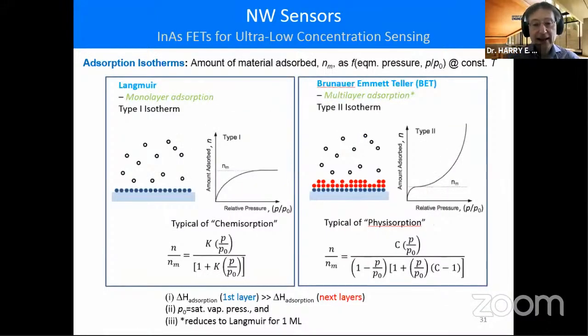I need to take a few minutes here just to deviate and make sure that you're aware of isotherms. So a very zero order look at that. If it were a single monolayer adsorption process, we would use the Langmuir isotherm, in which the amount of adsorbed material, Nm, is given as a function of its exposure. And that exposure is done in terms of the partial pressure to the saturated pressure at equilibrium. And obviously, once we reach the saturated pressure, then that monolayer is formed and you have this curve flattening off as shown. On the right is the multi-layer adsorption process, which is the normal process one would expect in the BET model, where we have adsorption occurring over many layers, typically a few monolayers at least, and the curve for that is shown at the bottom for this multi-layer process.